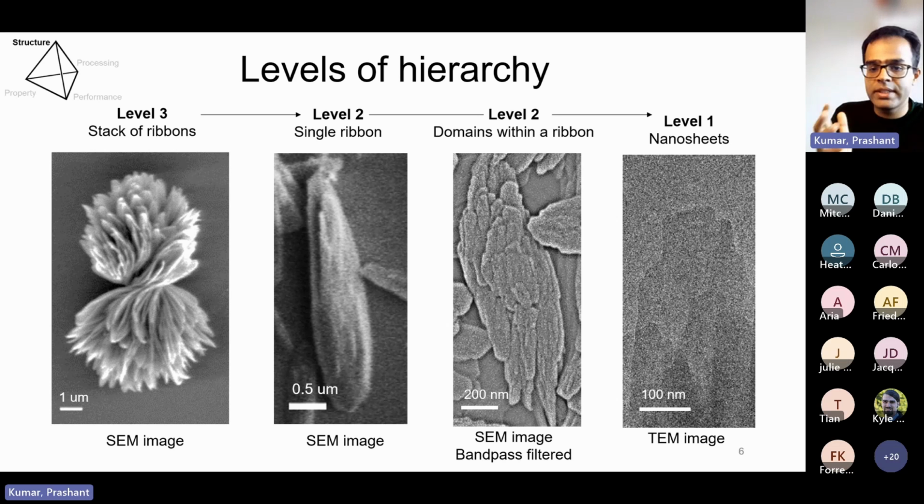That's the resolution limit of the SEM, where you can see up to only a few nanometers. Then we went ahead and looked at those individual domains within the TEM. And we found that they have these very thin layers, about 1.2 nanometers thick, stacked on top of each other. They are really thin because if you look at the SEM or TEM image here, you will see that in contrast to the carbon background, the sheets are barely visible. But they are there and they are really thin. And that is what this whole analysis tells us, that there are these 3 levels present in the system formed out of these thin sheets.